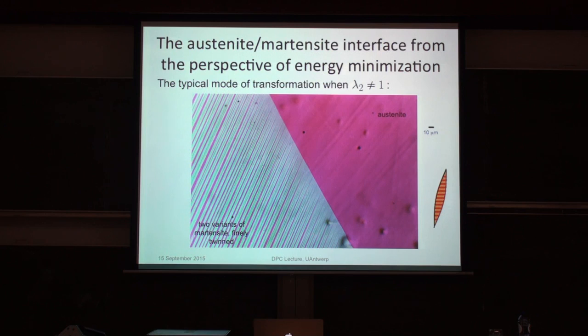And so another possibility would be to finely layer two variants of martensite. Now, when you finely layer two variants of martensite, you get many more possibilities for shape when it deforms. You can picture a zigzag like a fan. You get many possibilities of shape by layering two variants. And it turns out that if you layer them in exactly the right volume fraction, and you put this interface in exactly the right way, then you can make a very low energy transition layer between the phases. In fact, there's even a theorem that says that if you take the ideal shape changes and make this interface with just the right normal, which turns out to be irrational, then by making these twins finer and finer, you can drive the elastic energy in this transition layer to zero.